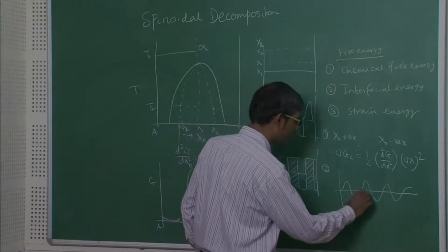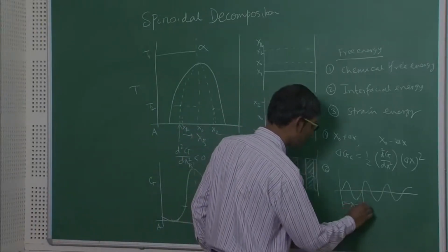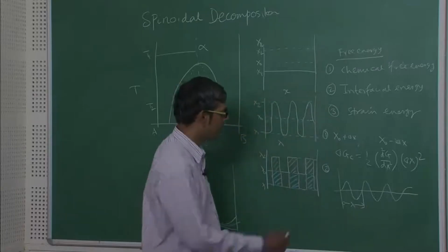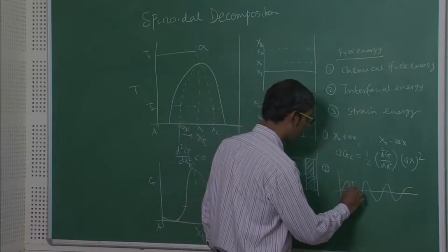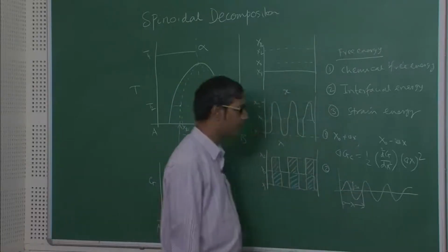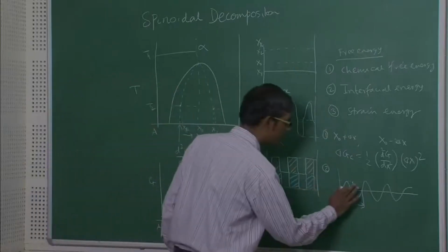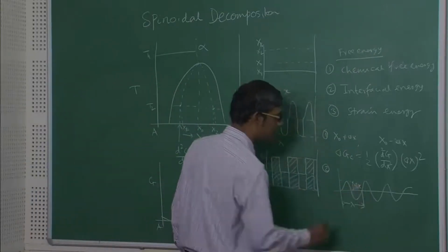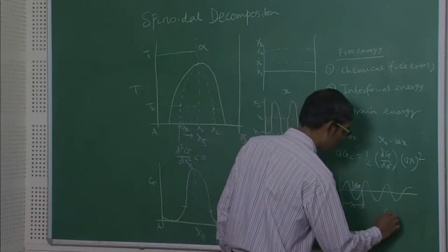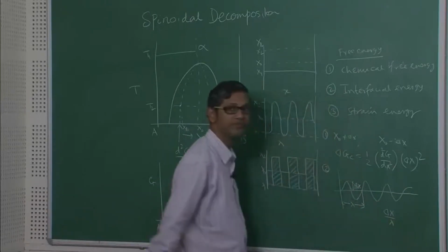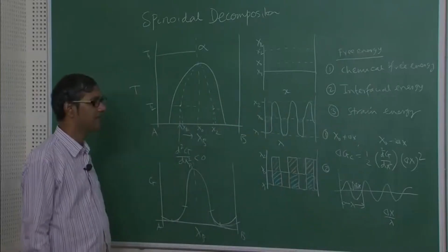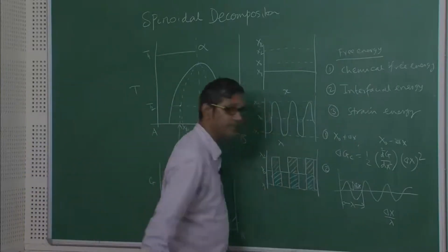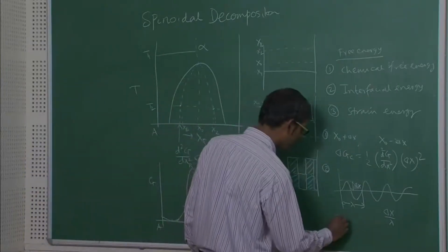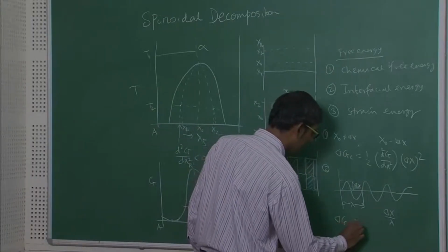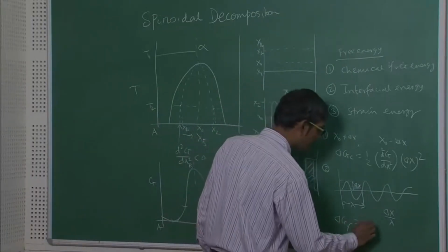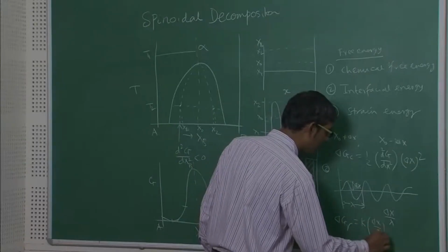So, if I have a wavelength of the sinusoidal compositional fluctuation of lambda and amplitude of delta x, as you see here, then it is very clear that the compositional gradient is basically nothing but delta x by lambda. This is the compositional gradient, correct. So, if I have such a compositional gradient, the energy of the interfacial system is basically a constant times delta x by lambda whole square.